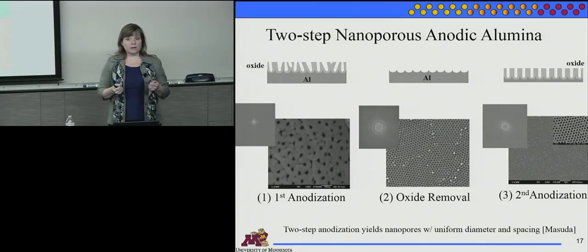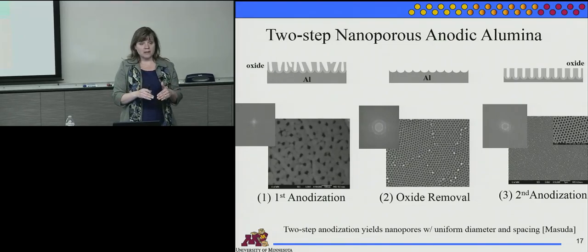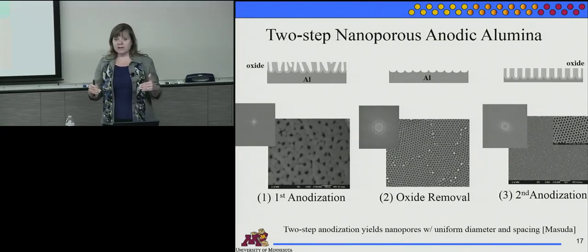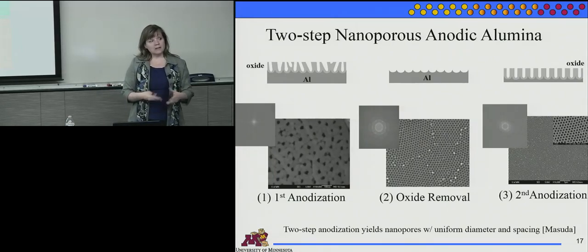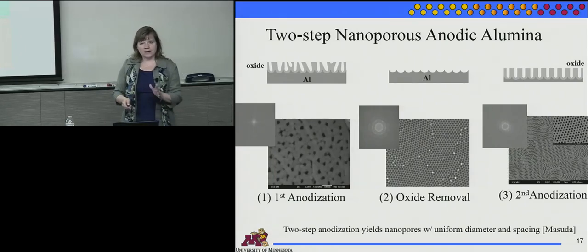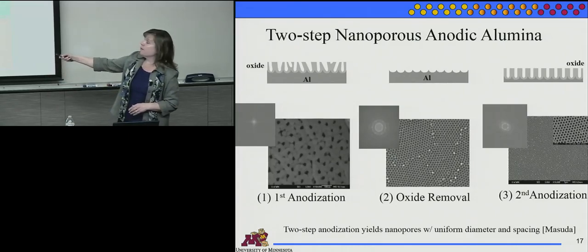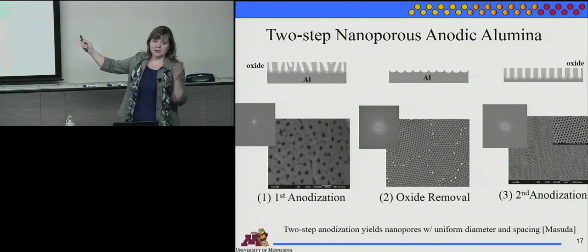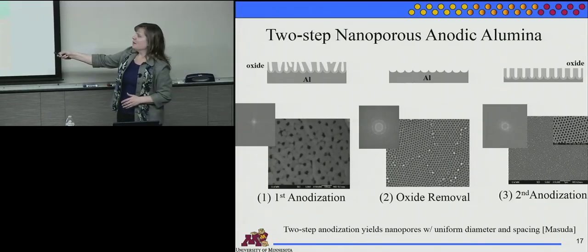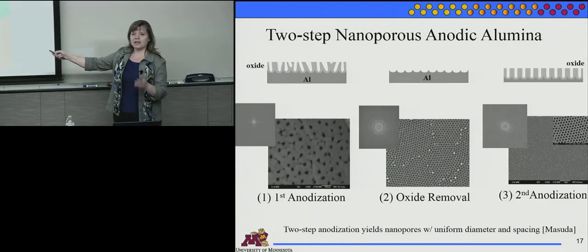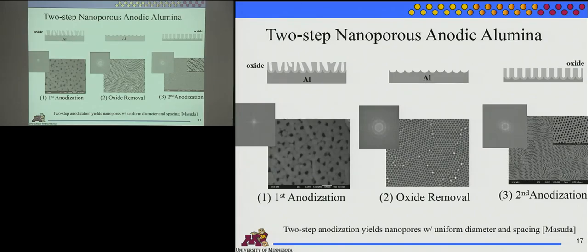If you're starting with an aluminum foil and you've got a bunch of grain boundaries, so a really rough surface, then longer is better. If you're starting with a film that you've deposited on silicon, it's fairly smooth, so you can go not so long and get pretty good quality. But in the case of a foil, which this was representing, you've worked 16 hours, then you etch the whole thing away. It's a bit of a bummer. But then when you start with this aluminum under the exact same voltage, temperature, electrolyte, all the pores have a place to start, and they just grow from there on. So that's when you end up getting very smooth sidewalls.